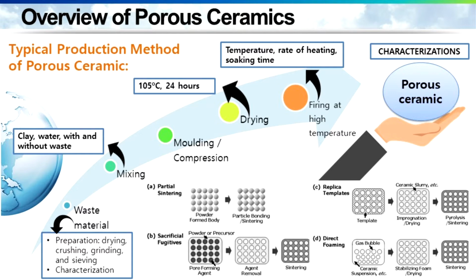The first stage is waste preparation, which includes drying, crushing, grinding and sieving of the waste material. Subsequently, the clay and waste materials will be homogeneously mixed, followed by drying and finally the firing process to produce the porous ceramic. Several mechanisms can be employed to form pores in the porous ceramic, which include partial sintering, sacrificial templates, replica templates, and direct foaming. The method selection is based on the desired final characteristics of the porous ceramic, such as percentage of porosity and pore size distribution.